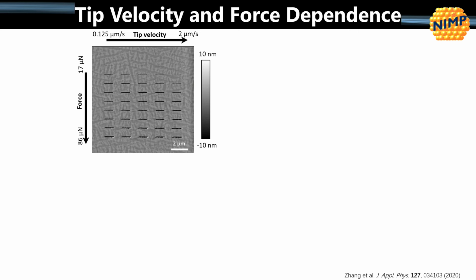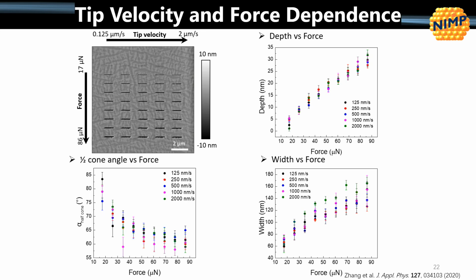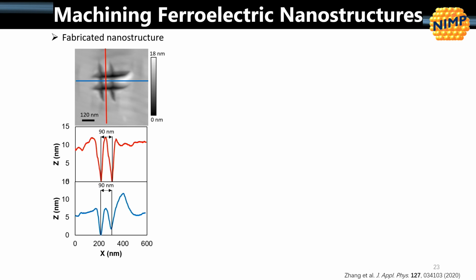Okay, so now that we know we want to do small lines, we varied the force and the tip velocity again. The tip velocity, again, didn't play a strong role, but the force, of course, does. So this is going to tell us what tip velocity and what force we should use if we want to make a very narrow structure. Pulling all of this information together, exploring the parameter space, allows us to then try to carve a small nanostructure, which we do here. In the end, this is around 90 nanometers in size.